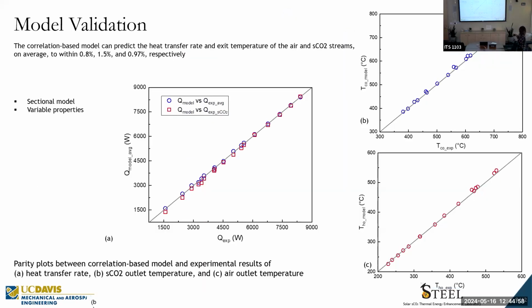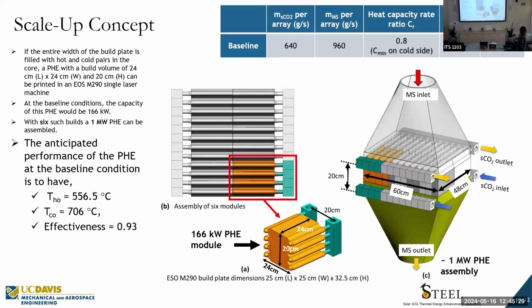And yeah, we ran the experiment and compared the thermal performance to the model that we had. There was a very good agreement. And so just to give you some numbers, for the exit temperatures on the cold and the hot side, we had about a 0.8 or 1.5% difference between the model and the experiment. And for the heat transfer rate, it was less than 1%. So this validated the model, and that was basically it.